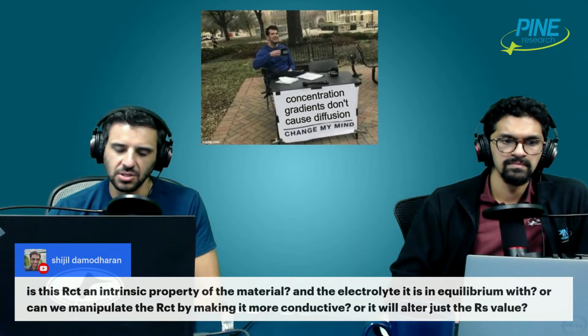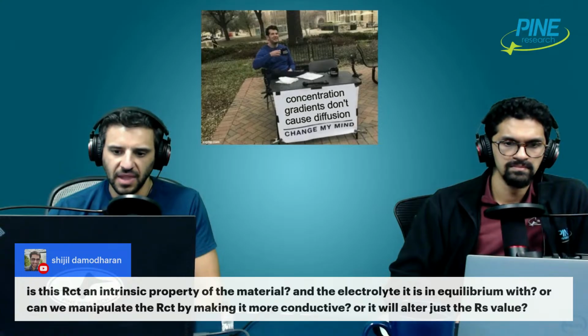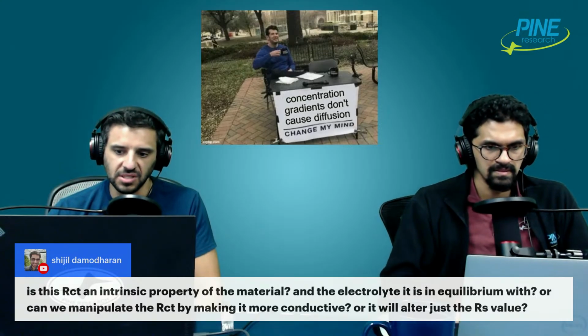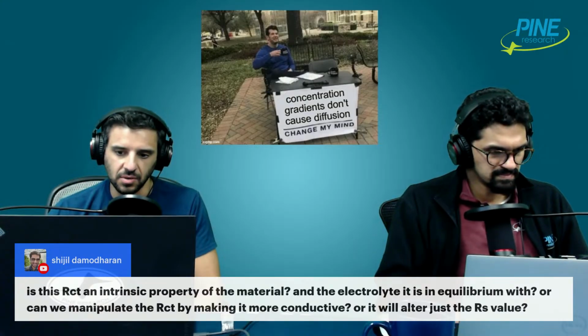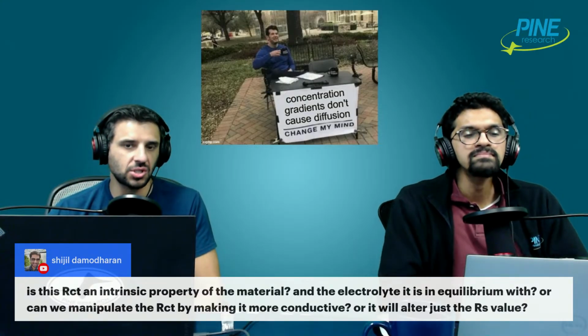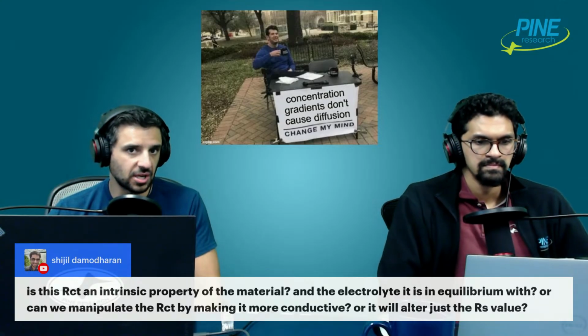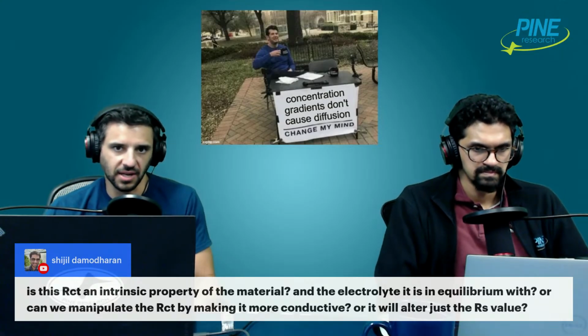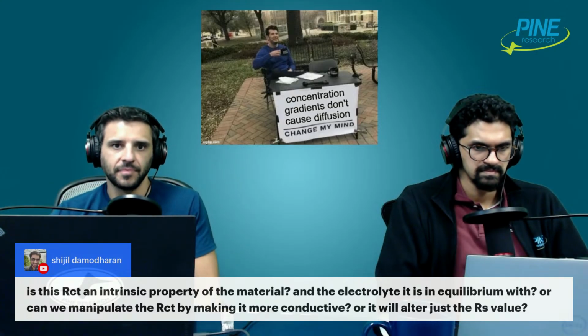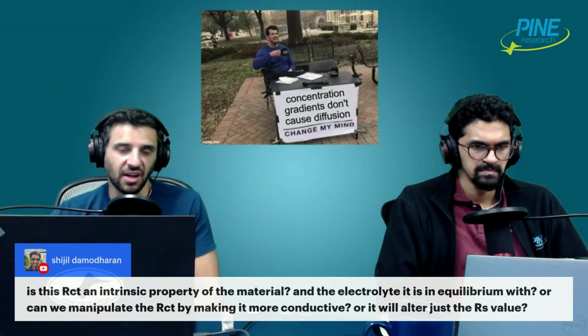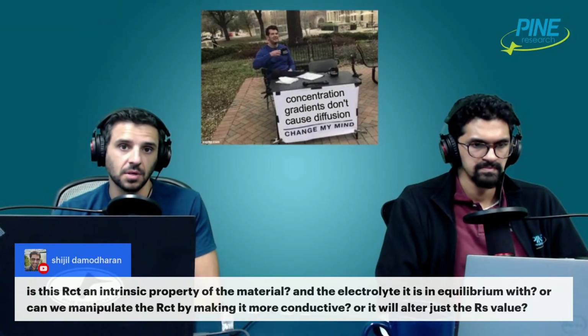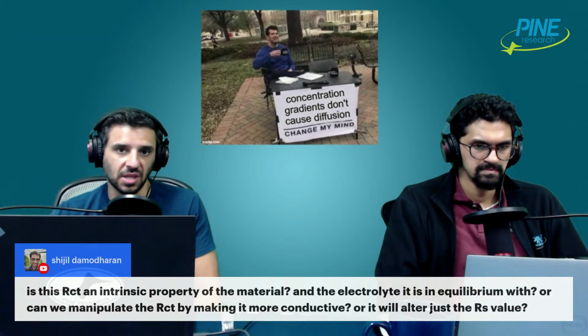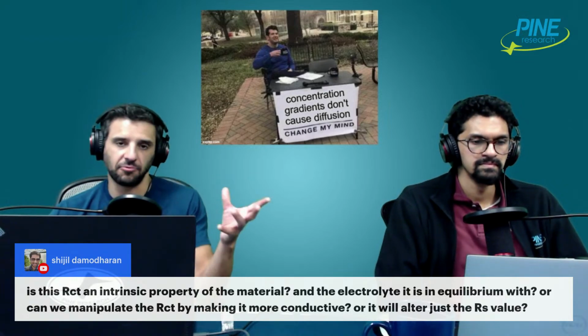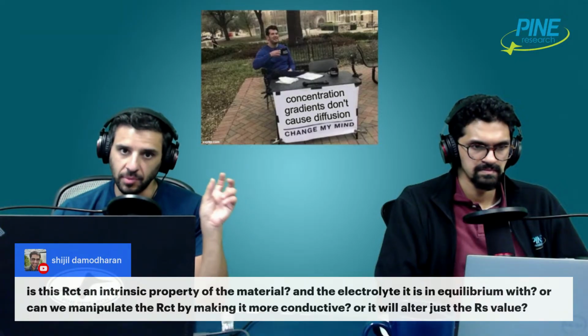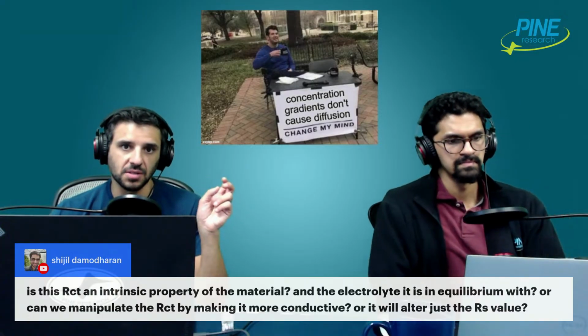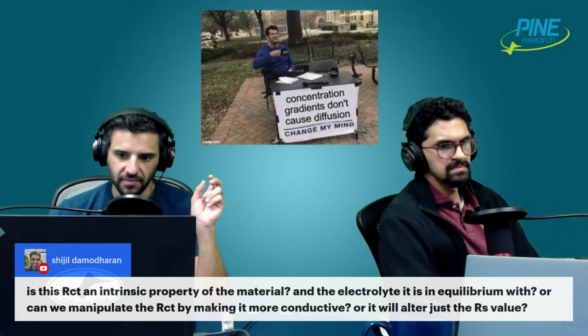RCT is a function of potential usually. I don't know if intrinsic is the right word. It is related to the material. It's the charge transfer resistance, so it's the ease or difficulty with which electrons are transferred from your material for the reaction that it's doing. That is certainly a function of the material itself, but it is also a function of the potential, the driving force. The potential with respect to the thermodynamic potential at which said reaction occurs, which is called the overpotential, is the driving force for that electron transfer.